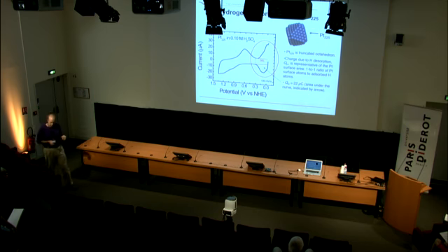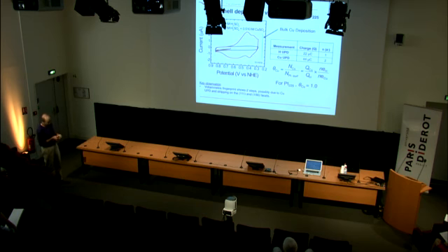Now what we're going to do is the same experiment on the same electrode, but with 10 millimolar copper in solution, do deposition and stripping, and measure the charge due to the stripping of copper. And we're going to compare it to this number, and then that should give us an accurate ratio of the number of copper atoms to the number of surface platinum atoms on the particles. And that's what this is.